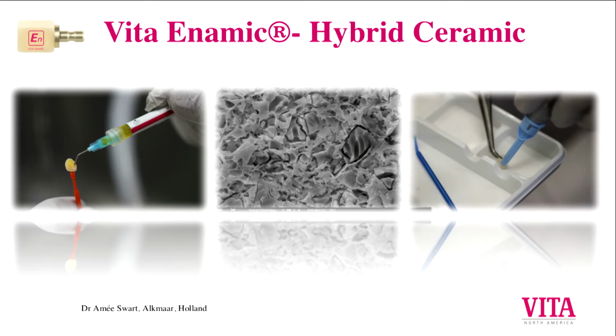And here you see, in this case we used Panavia aesthetic cement, 5% hydrofluoric acid for 60 seconds, and that's important, 60 seconds. To give you an idea, glass ceramic is only 20 seconds. So we've had a question. Can we over etch the Enamic material? If we etch for longer than 60 seconds, would it weaken the material?